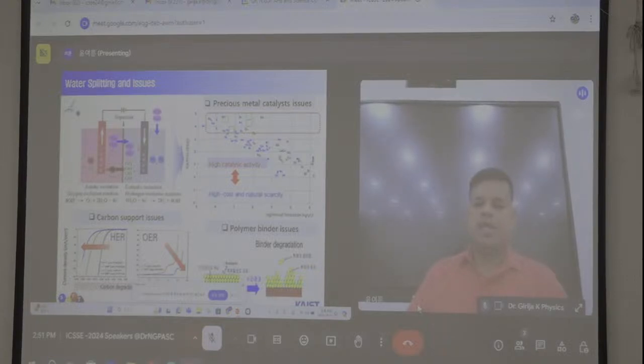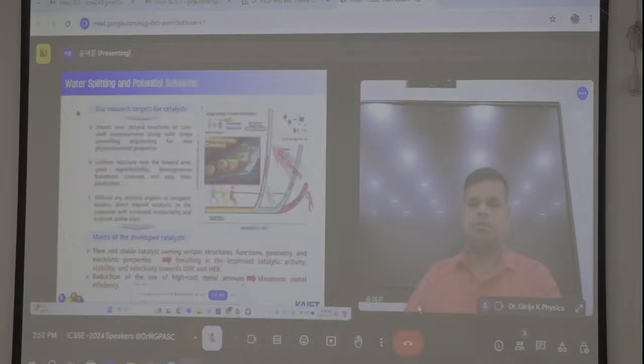So why does this happen? Usually for the HER and OER, the commercial material needs to be fabricated with some binders, because we cannot coat the material over current collectors like nickel foam, carbon cloth or carbon paper, so we need to use a binder. That binder may degrade during the long-term durability test. Therefore, the material may slowly dissolve and the performance will be lost, because the potential will be lost for both OER and HER. You can see the problem.